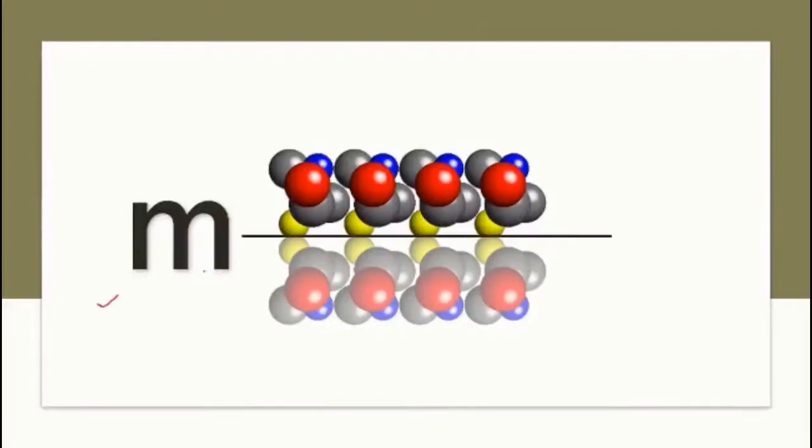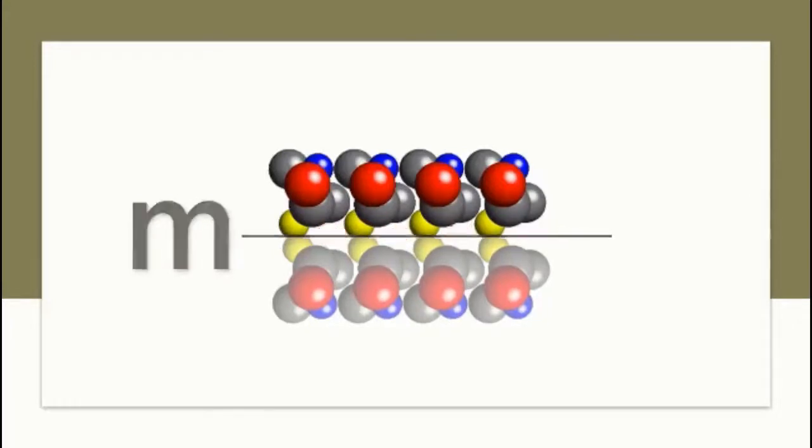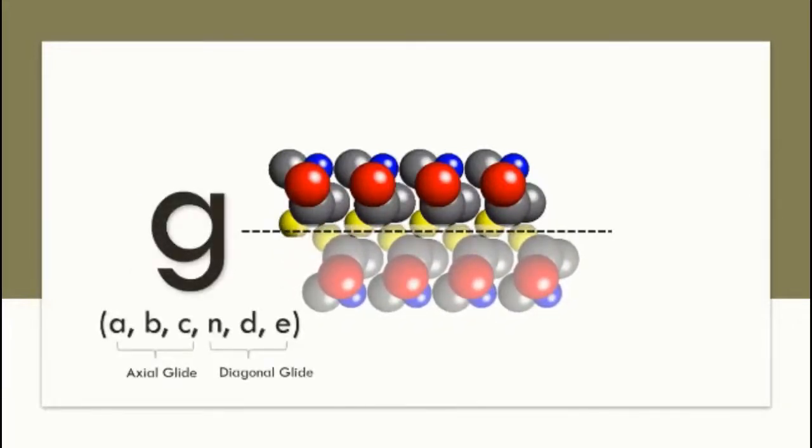Consider this packing of molecules. Here, we have packed the molecules using reflection symmetry. The gap is left in between two layers when molecules are packed just using reflection symmetry. The packing is much improved when molecules are packed using glide symmetry. In 3 dimensions, we have glide planes as symmetry element. Depending upon the direction of translation, 6 distinct glide planes are usually found in crystals indicated by symbols A, B, C, N and E. We are not going to discuss these glide planes in this lecture.